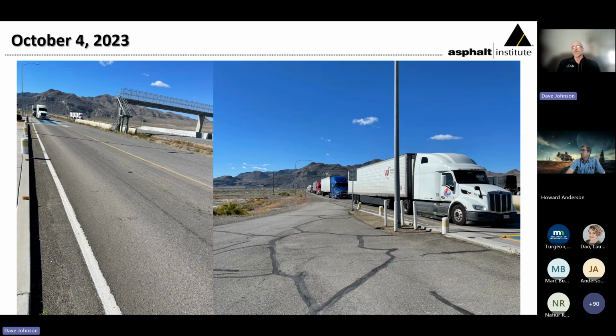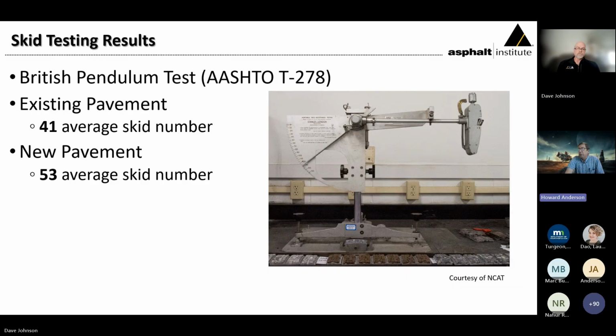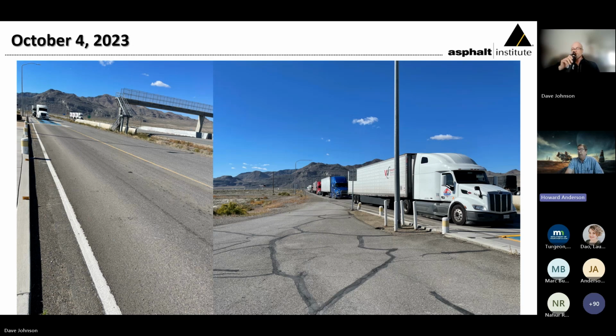Absolute recipe for rutting, especially in these hot conditions. And despite all that, the mix is standing up extremely well, and no rutting of any magnitude has been experienced. So Dave, let me add a comment. If you want to go back to that slide, Lonnie tried SMA in this place, and it lasted 6 months and it shoved, and they had to remove it. So for this to work under these loading conditions, Lonnie's comment was, if it works here, it will work anywhere.